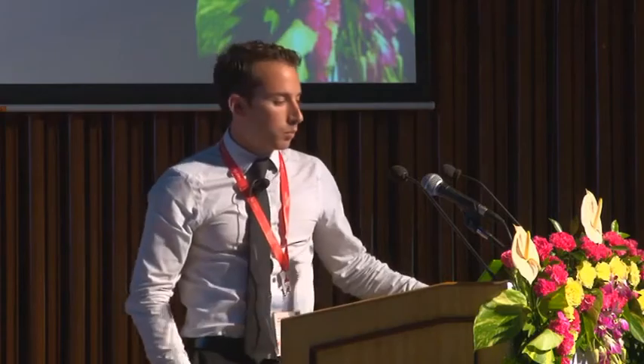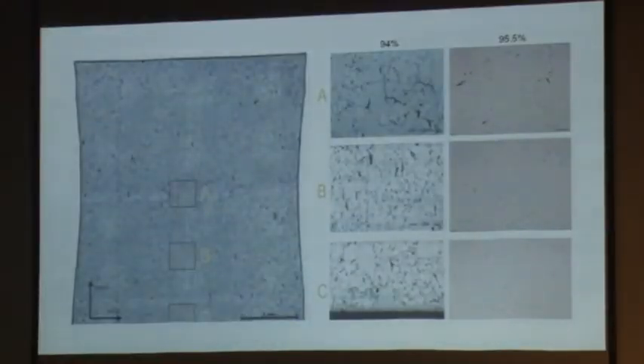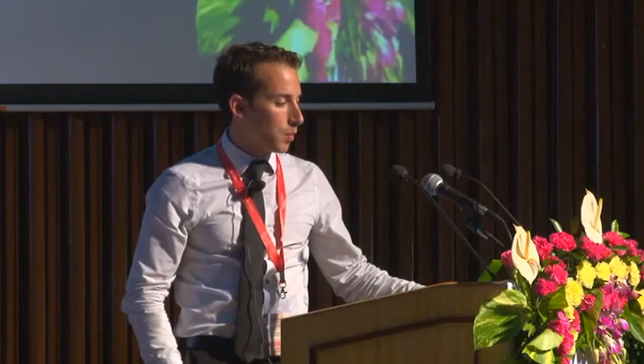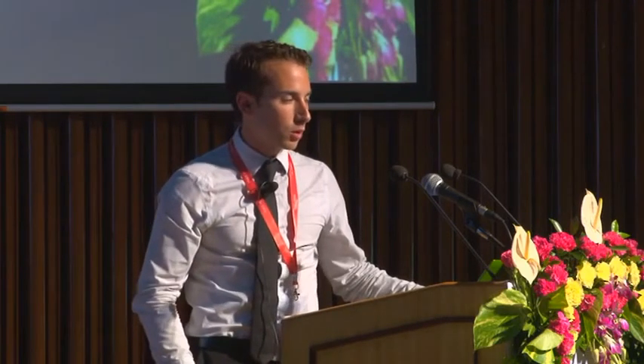And part of the steps in going towards a fuel that is considered ideal for irradiation involves several steps. This simply illustrates one of those single steps. Towards the end of the fuel manufacturing campaign for thorium-cerium fuels, we noticed that we had about a 94% density of that of theoretical density, and we needed to improve on this slightly. We noticed that we had a sort of an interconnected porous structure in the center of the pellet, and this is typical when you have sintering parameters that are somewhat non-ideal.